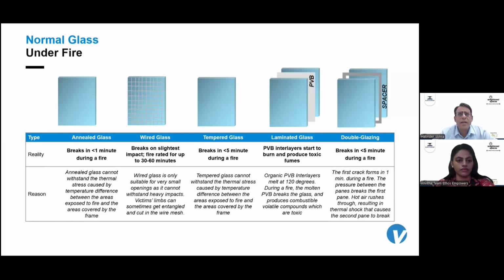Wired glass was where fire rated glass started, I would say. But eventually wired glasses have been phased out due to their drawbacks, and people getting hurt due to the wire mesh. They can go up to only 30 to 60 minutes, and that too for very limited sizes, not larger panes, when it comes to fire rating.